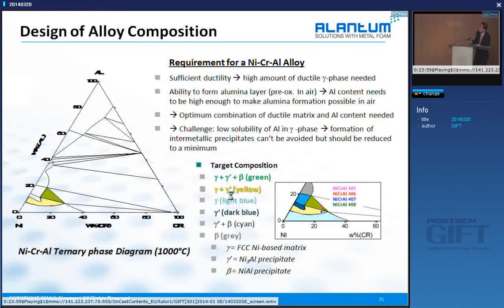Then, the basic requirement for the nickel alloy is, first of all, we need sufficient ductility. That means we need a high amount of ductile gamma phase. And the second is we have to have some aluminum. Aluminum is a kind of sealing, like oxidation. So we have to have some kind of alumina formation. This is a ternary diagram of nickel, aluminum, chromium, and finally we have to produce this gamma or gamma prime phase, showing in green. And somewhere there is a beta phase, that could be nickel aluminum, about 50-50 intermetallics.